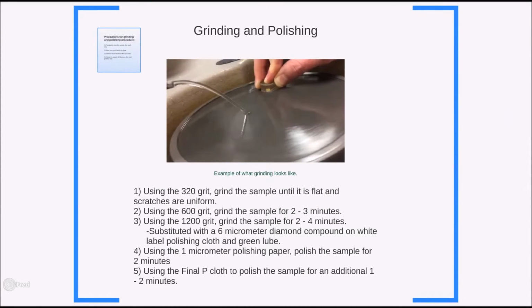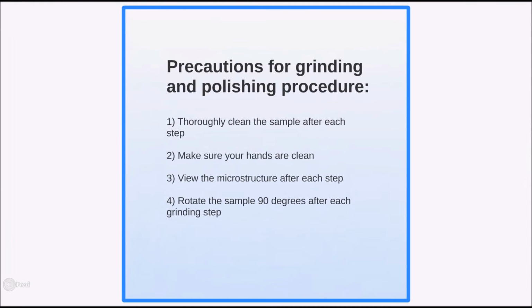Precautions for the grinding and polishing procedure include thoroughly cleaning the sample after each step, making sure your hands are clean throughout the whole process, viewing the microstructure under a microscope after each step of grinding and polishing, and rotating the sample 90 degrees after each grinding step to remove previous scratches.